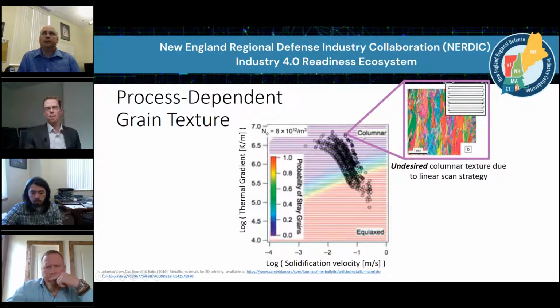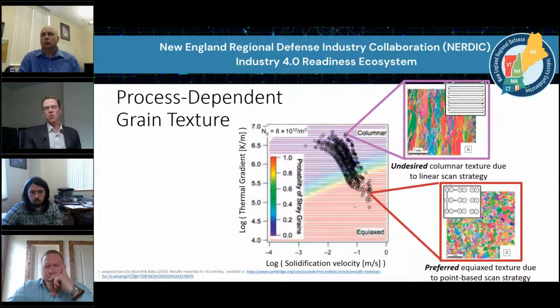So what does this mean? Up here in the purple region, with high thermal gradient and slow solidification velocity, you get what's known as columnar grains. Here is an image of these grains. You can see each color represents a different grain, and you get these very long, slender columns. Down in the red region, which is the equiaxed region, you get a more preferred grain texture in which they're almost more circular in shape.